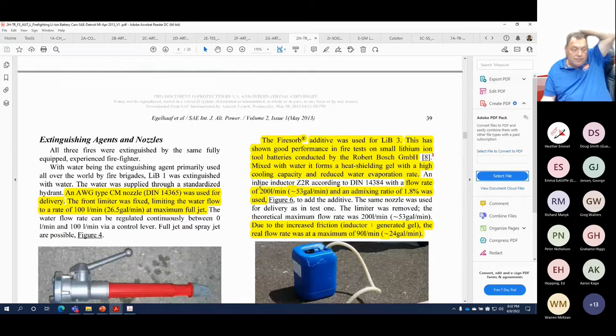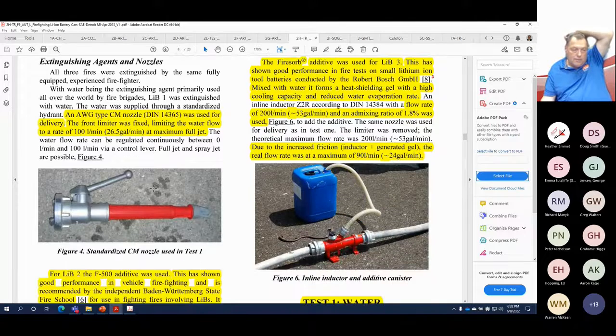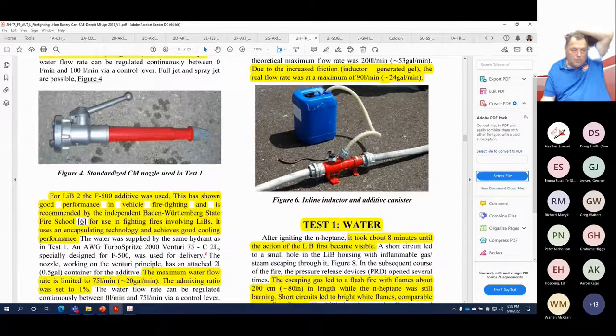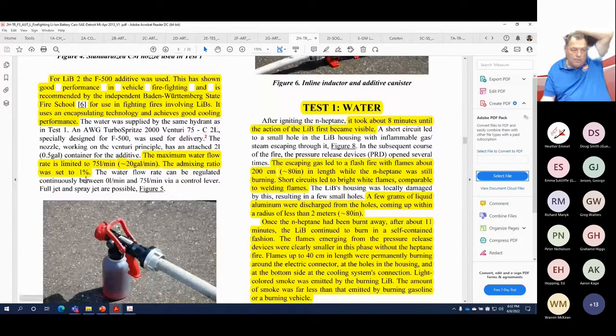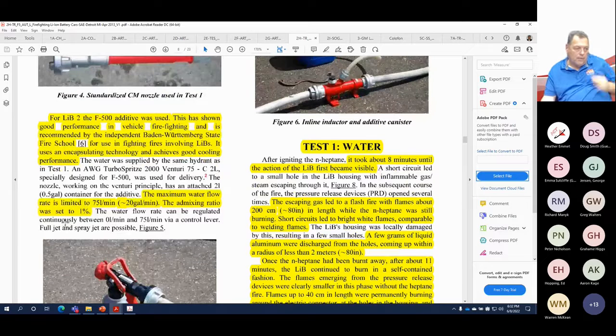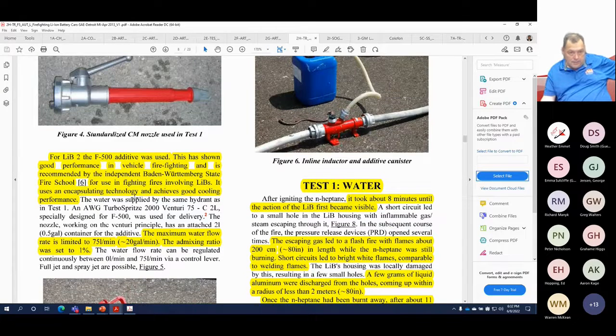It talks here about the different nozzle types that were used. This was a 100 liter per minute nozzle. Here we used the 75 liter per minute, used a ratio of 1% here. We actually, in Europe, they've been doing testing at 1 and 2%. Here in the US, we recommend 3% because our listing for Class B is 3%, and our encapsulation ratio is 2.5%, which I can address in a minute.